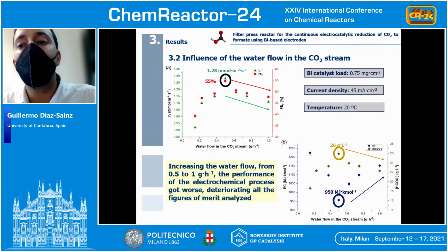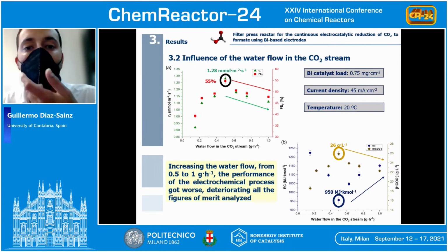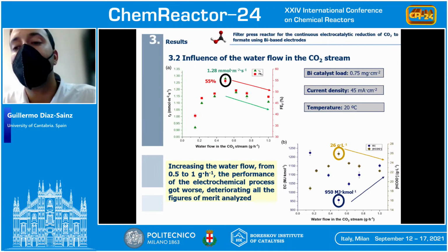In addition, we can observe that increasing the water flow from this point to 1 gram per hour, all the figures of merit, the formate rate, Faraday efficiency, energy consumption, and formate concentration, were worsening, and this is because the amount of water introduced in the carbon dioxide humidified input stream diluted the formate.